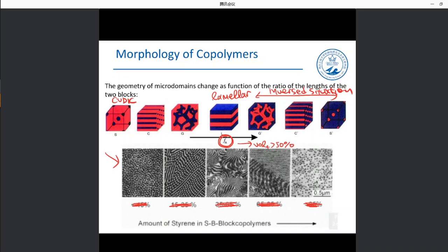but essentially it's very nice to see by TEM. This is TEM, we will talk about it in a bit, TEM images, where we can really observe this pattern in styrene butadiene block copolymers, for example. By varying the amount of styrene in there, we can create these tiny structures. This scale bar here has dimensions of 500 nanometers, okay? So you can realize how small these patterns are.